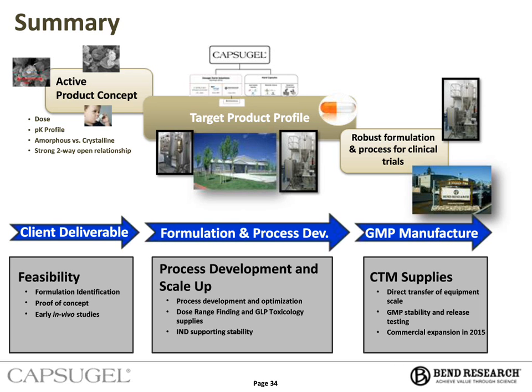There are cases where, with certain formulations or drug molecules, you might be able to push that as a truly single spray dried formulation, with loadings as high as 50, 60, 90%. And that coupled with higher fill weights into the capsule can start to deliver those much higher doses.